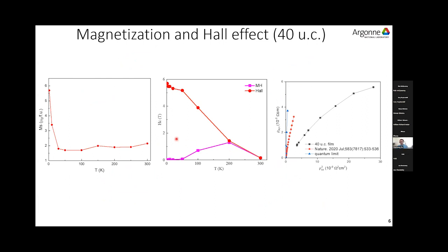So this is the summary of our magnetization and Hall measurements. Here is how the saturated magnetization changes with temperature. And here is the comparison of the coercivity we calculate from the Hall measurement and from the hysteresis loop. Although from the scaling law we show here, our sample is not close to the quantum limit, this whole assumption was based on a ferromagnetic order in the single crystal. From our measurements, the thin film seems to have a different magnetic structure. So we need more evidence to prove it.